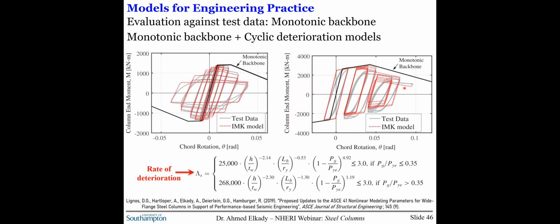And if you are a user of OpenSees and such, you're probably familiar with the Ibarra-Medina-Krawinkler model, or the IMK model for short. Essentially what we did here is calibrations of these proposed monotonic backbones with this model in order to calibrate the rate of deterioration, which is captured by this parameter called lambda. So again, you can compute directly the values for lambda here and use it with these proposed monotonic backbones. For different loading histories, you just need the monotonic backbone definition and the value for lambda, and regardless of the loading history, you are capturing the behavior very well, I would say.